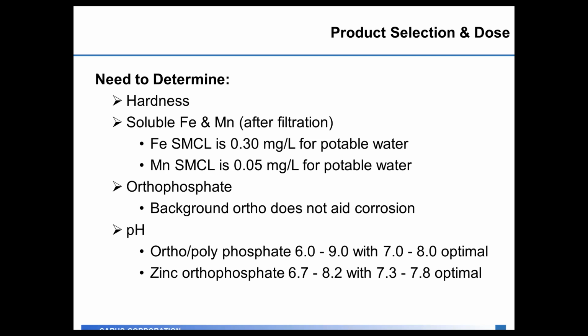Typically, the first things you're going to want to determine are what is the hardness of the water, what is the soluble iron and manganese after filtration, if you have filtration, going out the door to the consumer, and keep in mind that there are the secondary maximum contaminant levels for iron and manganese. Do you have any background orthophosphate? If you're a groundwater source, sometimes you will find that in your source water. You need to take that into account. And then what is the pH of your water going out the door to the distribution system? For a blended phosphate of ortho and poly, pH 6 to 9 will work, but it's optimal between 7 to 8. If you're using a zinc orthophosphate, a pH of 7.3 to 7.8 is optimal. So those are some of the things you need to take into account.